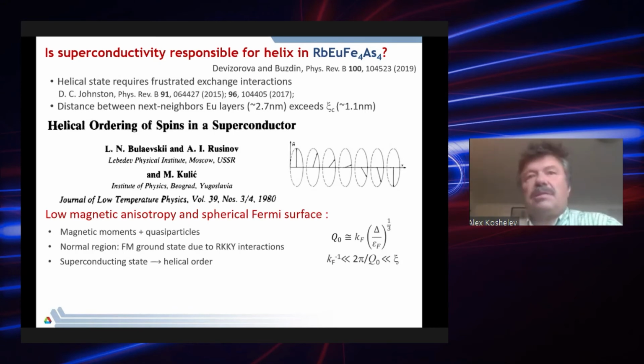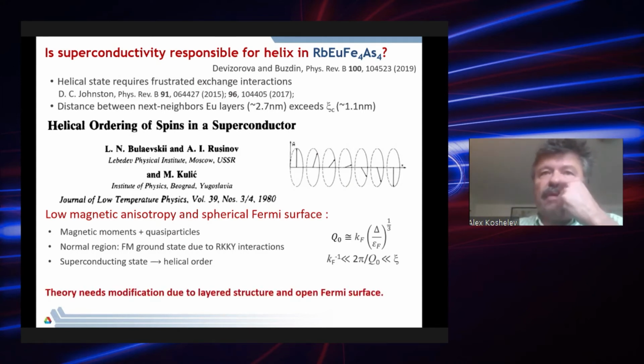And then the natural question is whether the mechanism is similar to the old mechanism predicted in this old classical paper. In that mechanism, it was considered that the magnetic moments and quasi-particles in the normal region, it was supposed that the superconducting state is ferromagnetic and caused by RKKY interactions, and modification of this interaction in the superconducting state leads to helical order. And even if this general theoretical picture is correct, the theory still needs many modifications because of the layer structure and open Fermi surface of this material.